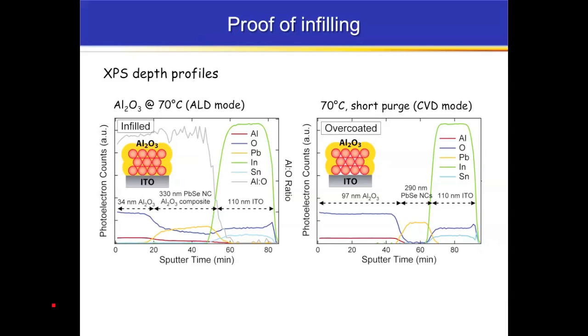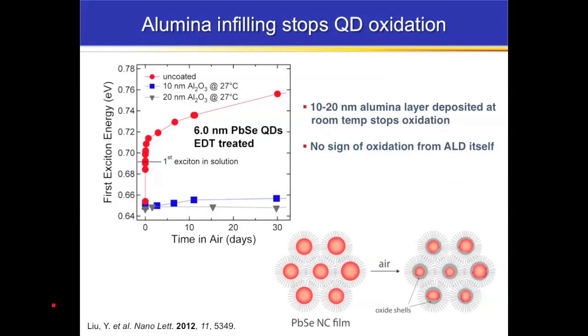That tells us, along with a lot of other data, that we have an infilled material here as opposed to an overcoated material if we slightly change the process. This ALD infilling technique basically completely shuts down oxidation of the dots, and we can monitor oxidation again optically. If you look at oxidation of a film with no ALD treatment, you can see that you get this blue shift effect over time in air. This is because the dots start out pristine, but over time they build up these oxide shells around them, and that gives us a larger gap.